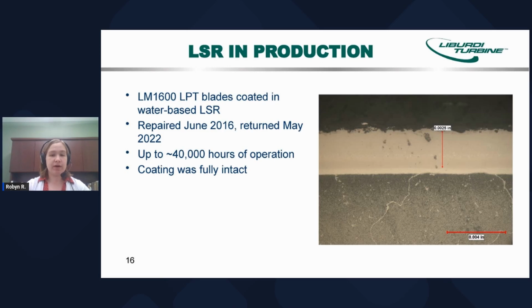We were able to see from our analysis that the coating was fully intact, plenty of beta aluminide still remained on there, and no large damages had occurred. Being able to get this active feedback helps us with our process of continuously being able to monitor and improve our LSR slurry.